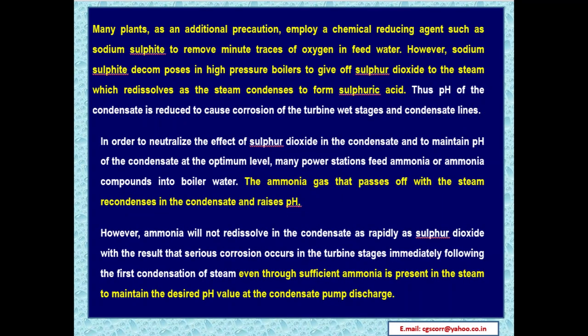Many plants, as an additional precaution, employ a chemical reducing agent such as sodium sulphite to remove minute traces of oxygen in feed water. However, sodium sulphite decomposes in high pressure boilers to give off sulfur dioxide to the steam, which redissolves as steam condenses to form sulfuric acid. Thus, the pH of the condensate is reduced to cause corrosion of the turbine, wet stages and condensate lines.